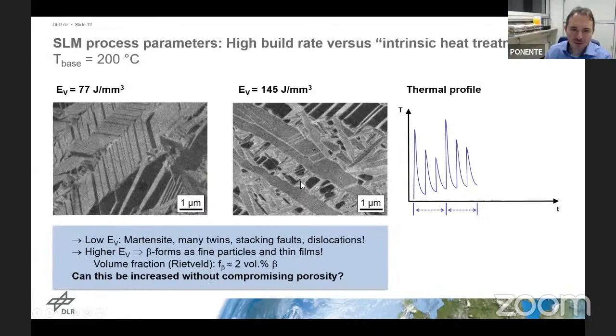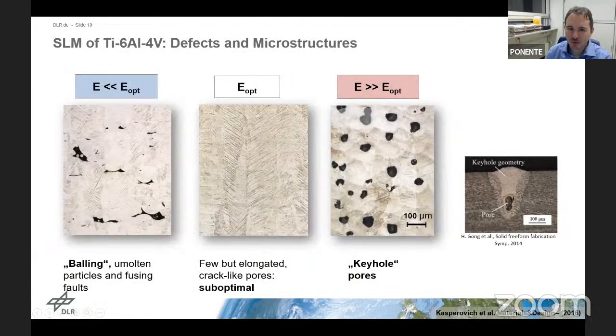Yeah. So the effect is mostly on the fatigue side of things. Think in terms of stress concentrations. If you have very, very sharp edges at these pores, the balling pores, for instance, where you have unmolten particles and poor fusing of different layers, you have very high stress concentrations at the edge, which can aid or enable easy crack nucleation. So materials with this kind of pores, on the one hand side, the pores are very big because they correspond to the size of powder particles. So 50 microns or so, and larger. And their shape is very, very critical. So this kind of material you really want to avoid.